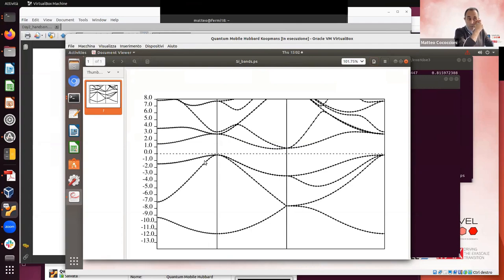So what you end up doing is putting a sizable V on states that significantly double count electrons in the bonding region. Since this material has a significant amount of charge density in the bonding region, the error becomes significant as well.